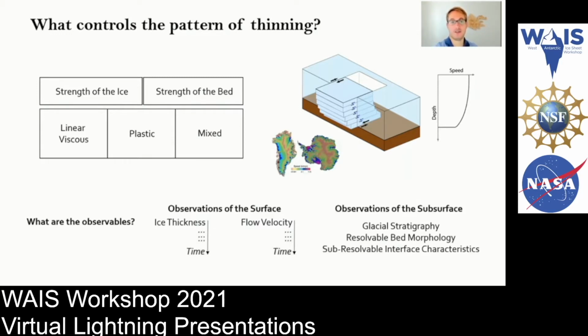Historically, we have not had enough information to constrain all of these unknowns. And so we assume a sliding law, and then we use things like ice thickness and ice flow speed to invert for the strength of the ice and the strength of the bed. But as the poles become more information rich, both from time-dependent satellite observations and from denser geophysical observations of the subsurface, it would be ideal if we could use this new information to further constrain the problem.